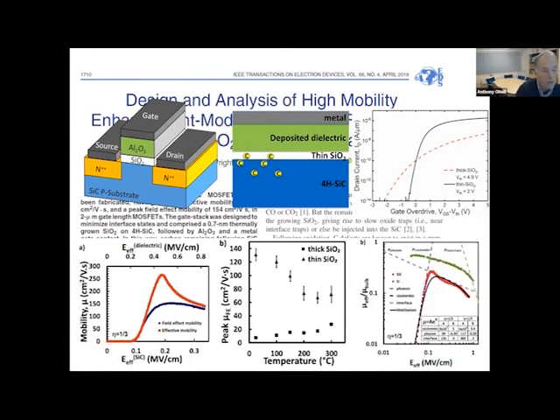And then this final plot is a universal mobility curve, which is much loved by people in the silicon electronics community to try and see how things like strain silicon that we worked on allowed us to move beyond the normal universal mobility. So this is a plot of mobility against effective field, which effectively is gate voltage. And you have different contributions to mobility in any material system. So you have Coulombic scattering, you have phonon scattering, which is very material dependent, and surface scattering, which is particularly important at higher gate voltages.